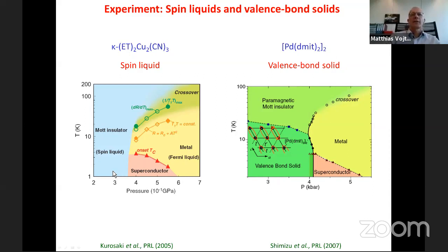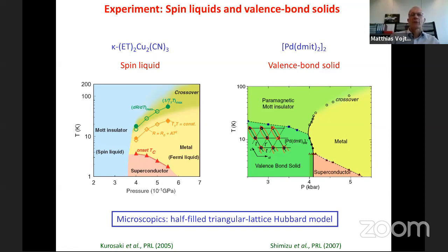And what you see in all cases is that if you start at ambient pressure from the insulator, at high pressure you go to a metal. And in between, there is also a superconductor. And on the left-hand side, this insulator doesn't show any symmetry breaking down to very low temperatures. So this is a spin liquid. Whereas here on the right-hand side, there is a symmetry breaking phase transition, and the low temperature state is in fact a valence bond solid, where you have dimerization of the type as shown before. So as I mentioned, in both cases, the microscopic description is in terms of a Hubbard model on the triangular lattice.